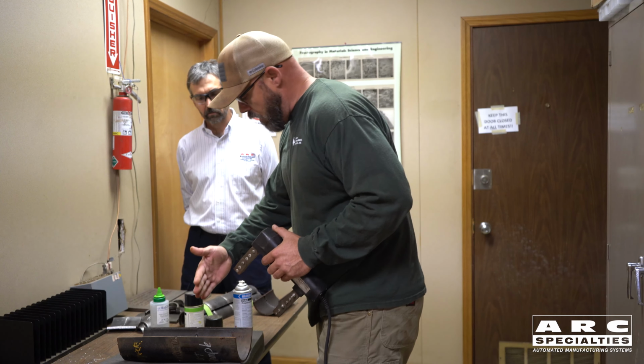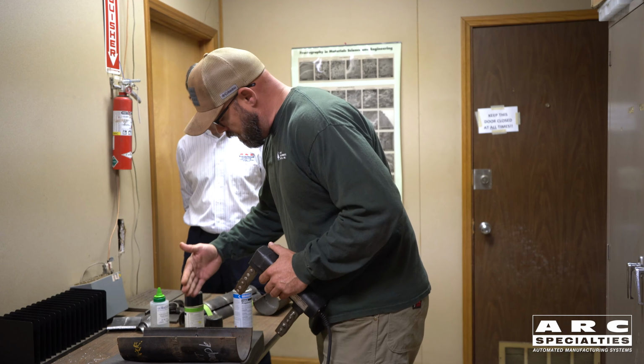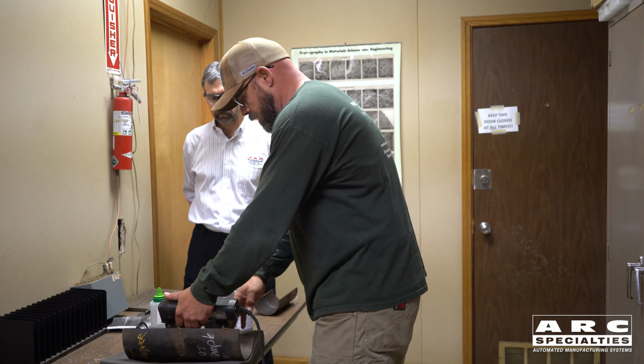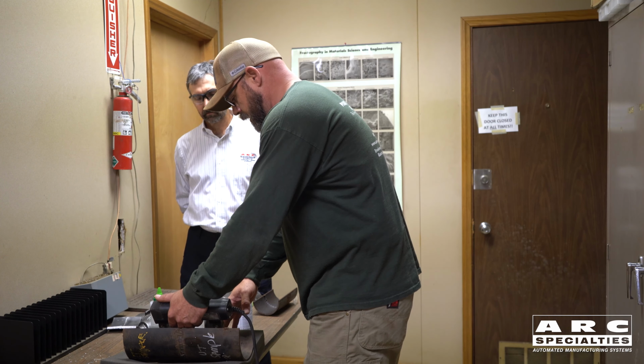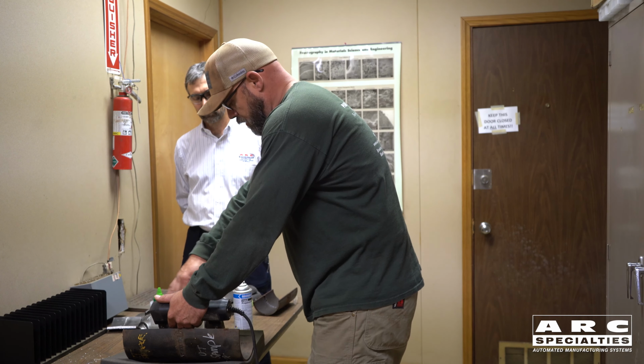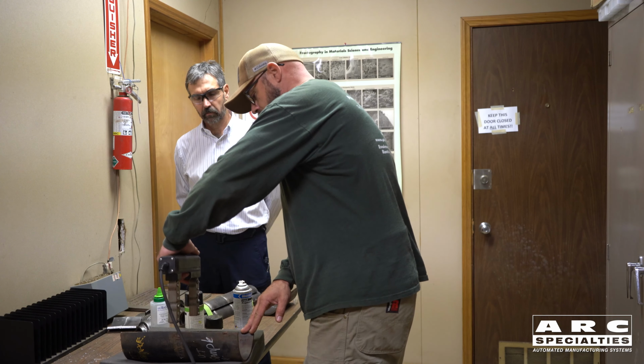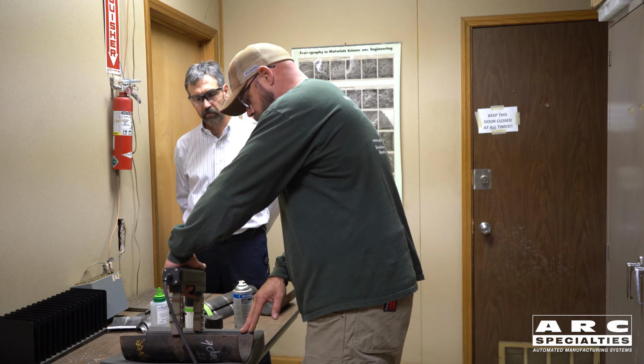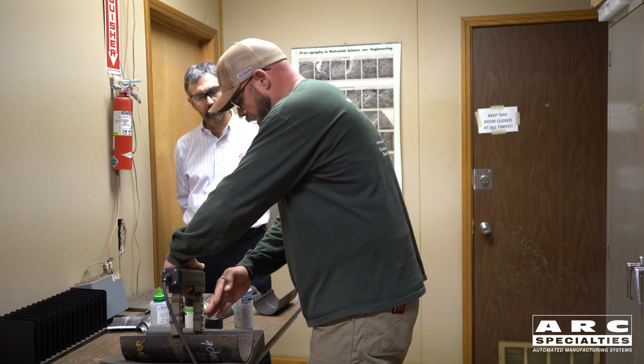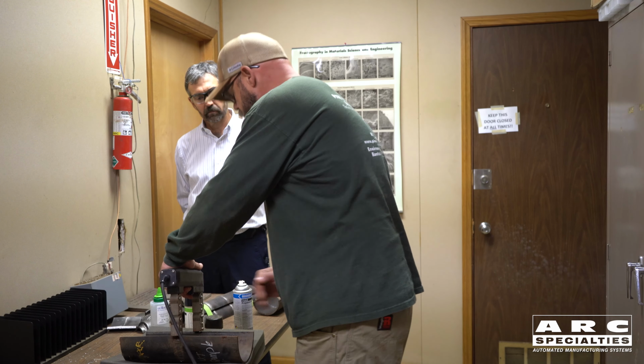So you've got a longitudinal, leg to leg indication. So if you're looking for an indication that is parallel to the weld, you would want to go 90 degrees, like this. So you have to rotate it once to get full inspection? Yes, you've got to do 90 degrees here, perpendicular to the weld, and then you're going to go 90 degrees parallel to the weld to get your parallel indications or your transverse indications.